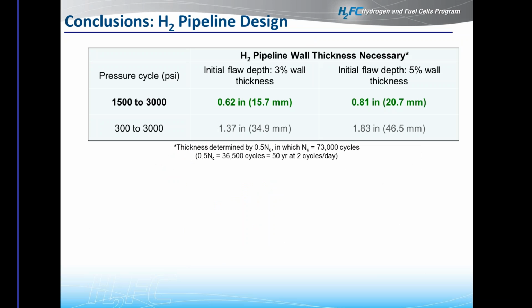So now we've measured the fatigue crack growth behavior, and we can use that to help calculate what minimum wall thickness may be needed for hydrogen steel pipes. So what we did was we said, okay, we want to have a pipe that lasts 50 years, and we would assume that we have 2 cycles a day occurring on that pipe. There are many variables that affect this, but the 2 that have some of the most dramatic effects are, first, the pressure ranges that we're actually testing at. In this case, in bold, we see the 3,000, this would be a pipe cycling between 3,000 psi down to 1,500 psi twice a day for 50 years.